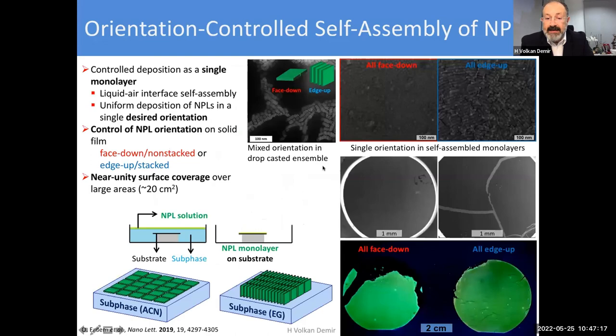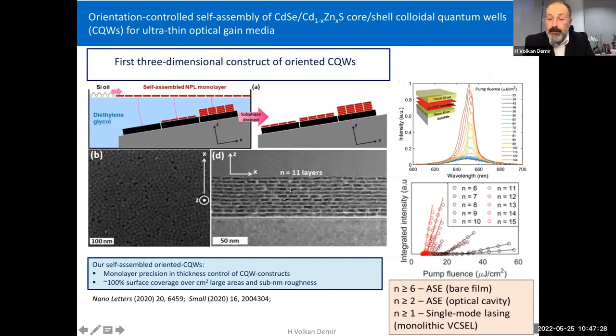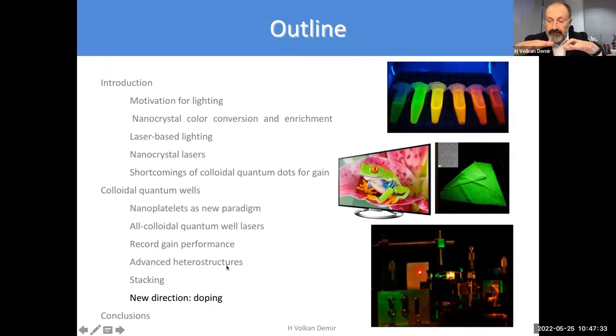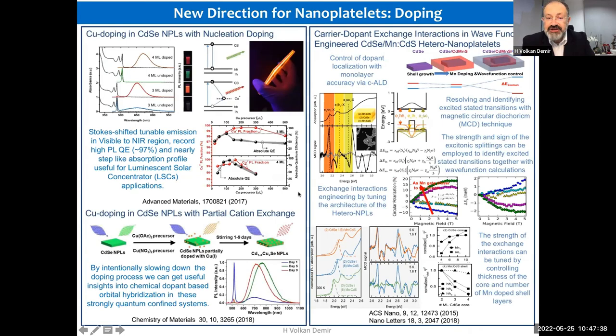And this allowed us to show quite continuous, non-disrupted operation for more than 10 hours. And these material systems now, we put in ensembles, all face down or edge up, to make even better devices. This is what it looks like. We can actually build them up. This is the cross section. And these materials, in addition to well-controlled orientation, we can dope them. And this is also a very new direction we are exploring. This brings me to the end.